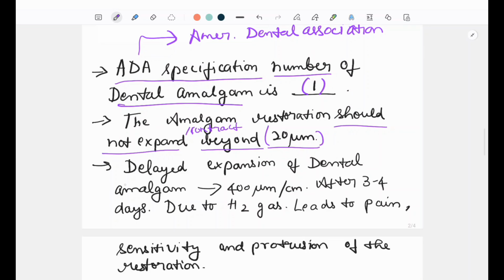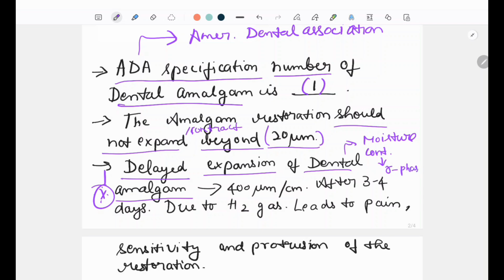Here we have an important point, that is delayed expansion, which is very commonly faced in dental amalgam restorations. Delayed expansion of dental amalgam occurs when there is moisture contamination during the gamma phase formation. If it does occur, it can go up to 400 micrometers per centimeter after 3 to 4 days of restoration. This occurs due to the hydrogen gas formation.